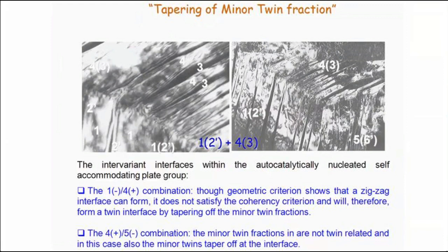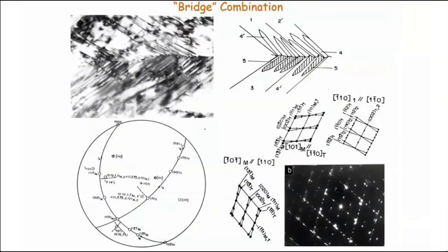If I turn it around and say, this is the evidence that there is something happening at the microstructural level in order to obey this condition, that there is what we call a twin interface, which is derived from a mirror plane of the parent phase. And if I go across,